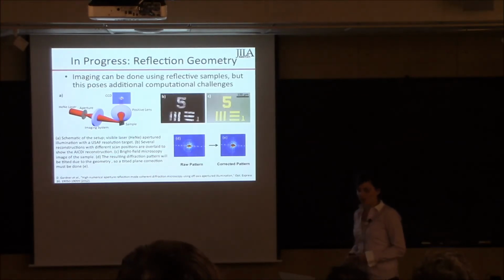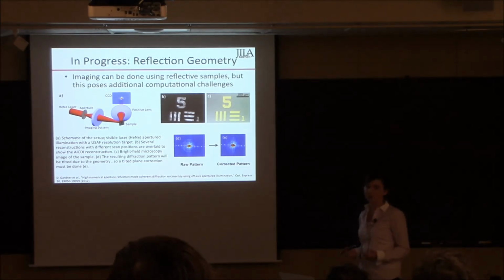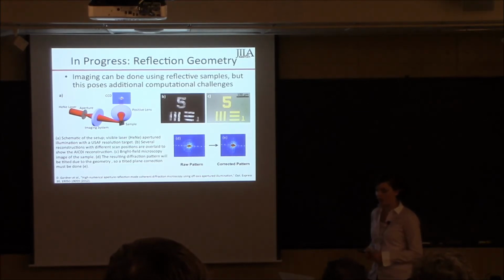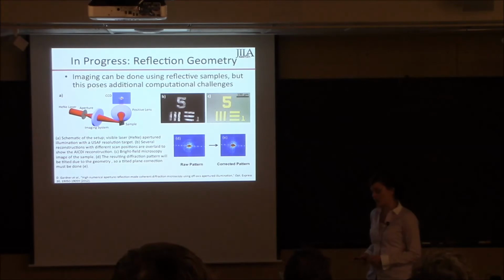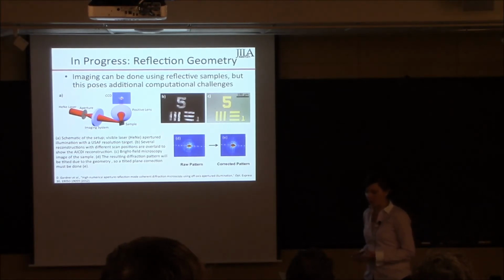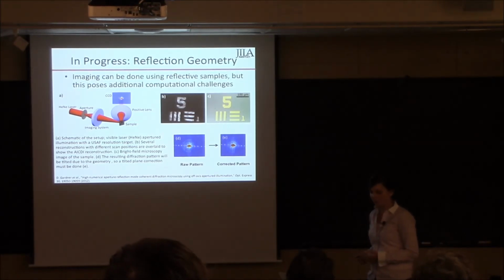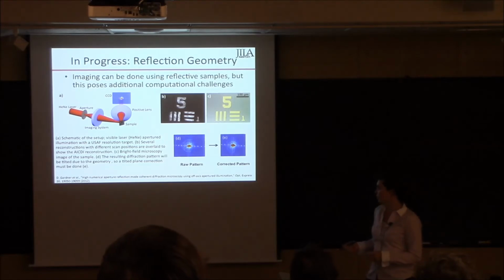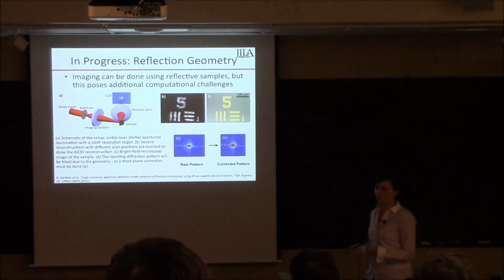So now all of the experiments that I've been telling you about so far were done in what's called transmission mode, which is where the light passes through some part of the sample. But sometimes we want to image a sample that is very thick or that is not transparent to EUV. For example, patterned wafers that are commonly used in the semiconductor industry aren't necessarily transmissive to EUV. So if we want to image something like this, we can put it in a reflection geometry, which is where the sample is placed at, for instance, 45 degrees, and the light is reflected off of it rather than being